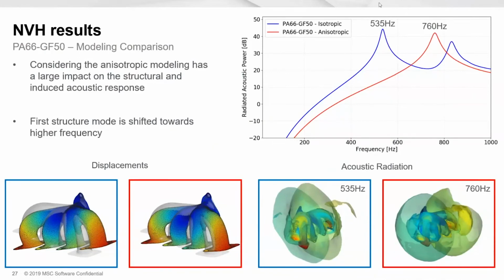So on the top right, we look at the radiated acoustic power. The blue curve is the isotropic response and the red one is the anisotropic one. So we see a shift in the modes, which is typically what we can expect as soon as we introduce anisotropy, so a more precise behavior of the structure. We simply shift the structural response, and this is reflected in the vibration and finally in the acoustic response as well. Moving to the next slide, we perform the parametric study.